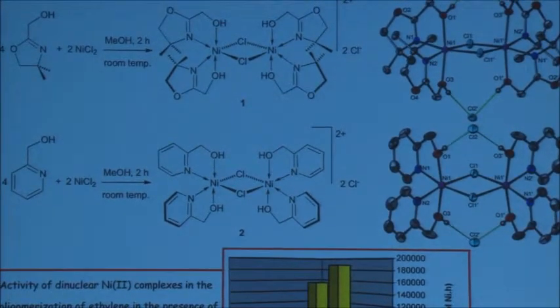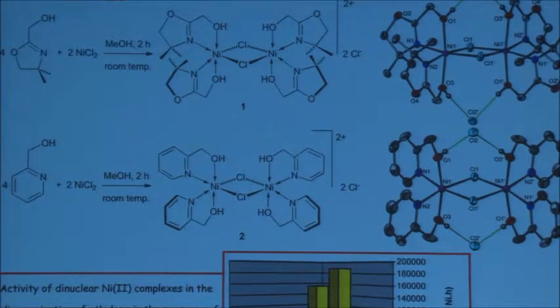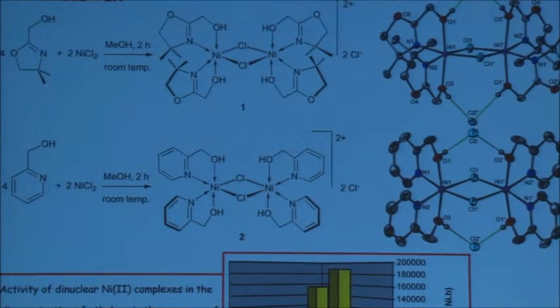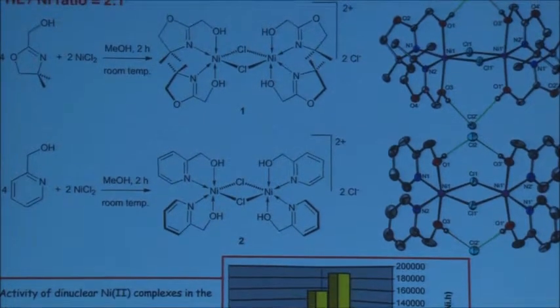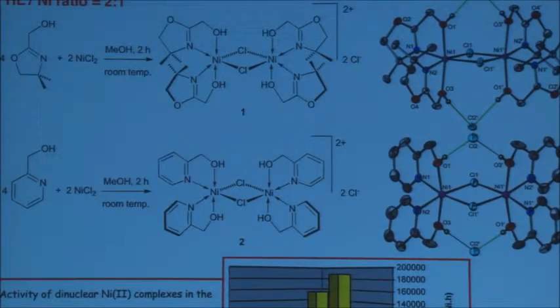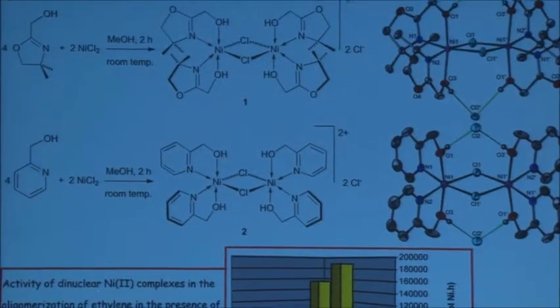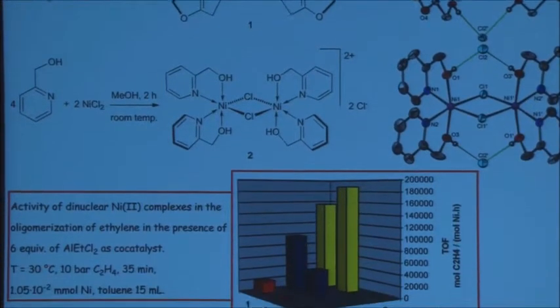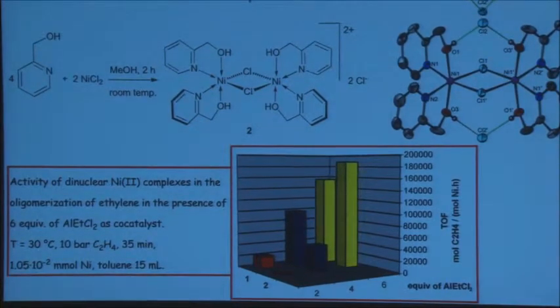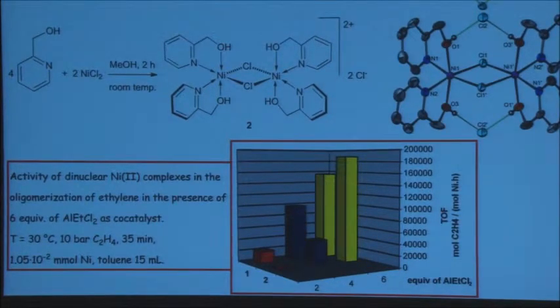Now, in terms of catalysis, we performed them under comparative conditions to be able to draw some conclusions. It's always difficult in catalysis, but at least you do your best. We tried to look at the activity of the system for oligomerization: 30 degrees, 10 bars ethylene, 35 minutes. That is standard conditions in our lab.